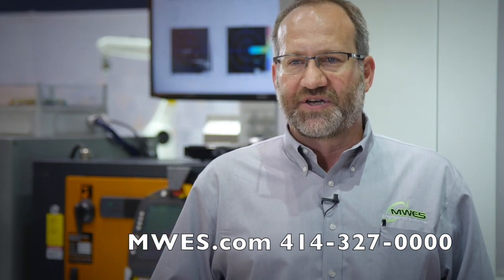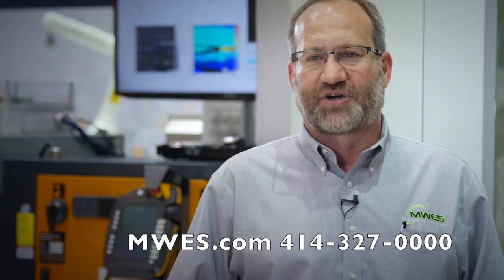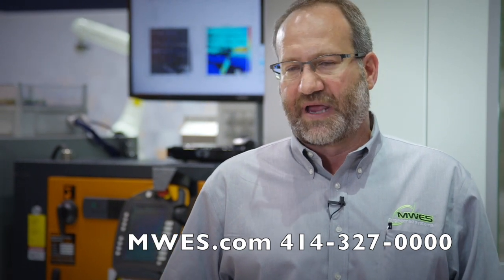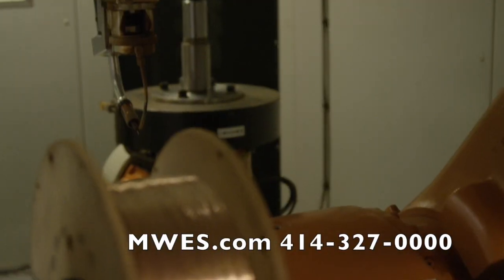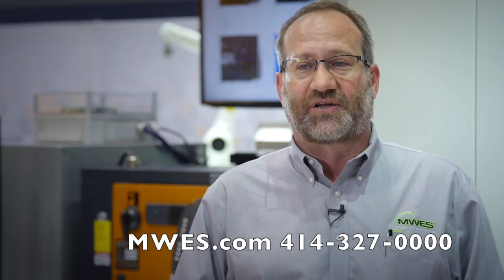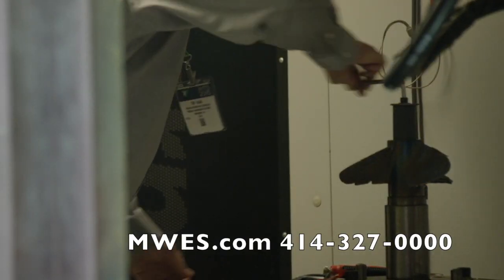We're looking at roughly 1/20th to 1/25th the price of powder, because the cost of the material for a powder material is $12 to $25 per ounce, where the material that we're using in these applications is $3 to $15 per pound in the wire application. Plus, we have many more different metallurgical characteristics in the wire available as a standard product than you would in a powdered component. Our deposition rates are also 20 times faster.